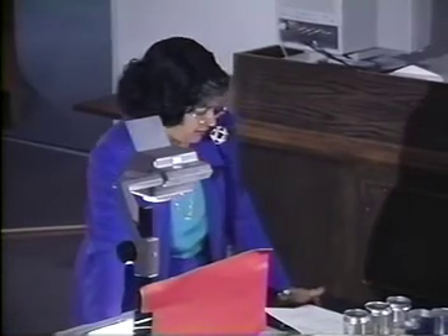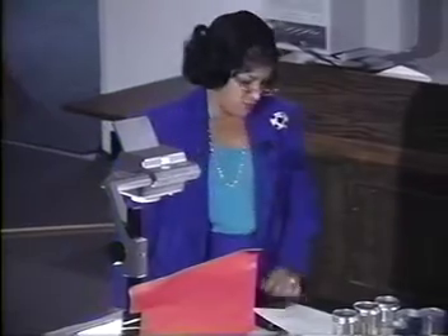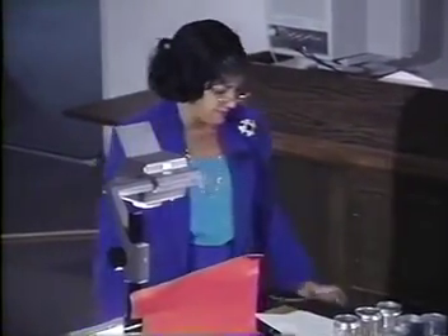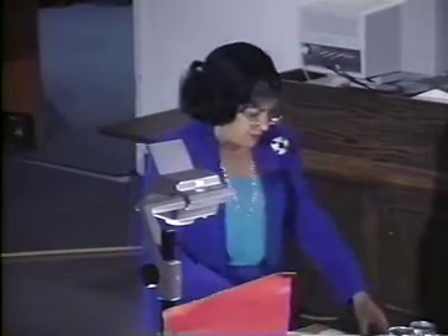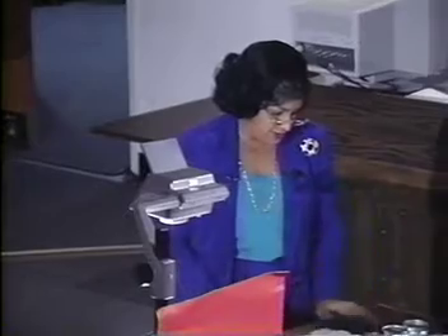It also has a very, very high strength to weight ratio, which is nothing more than the tensile strength divided by the density. And it falls into a category of materials that we call non-ferrous materials, not based on iron. Metals we break into 2 broad categories: those based on iron, your steels, your cast irons, and those that are not based on irons, your aluminum, your nickel, your titanium, your zinc, your copper, your lead. So aluminum is one of the non-ferrous materials.